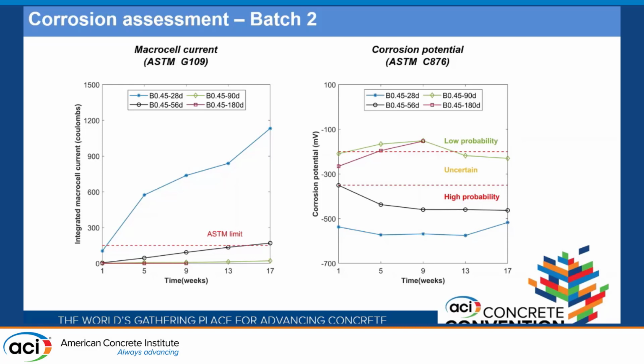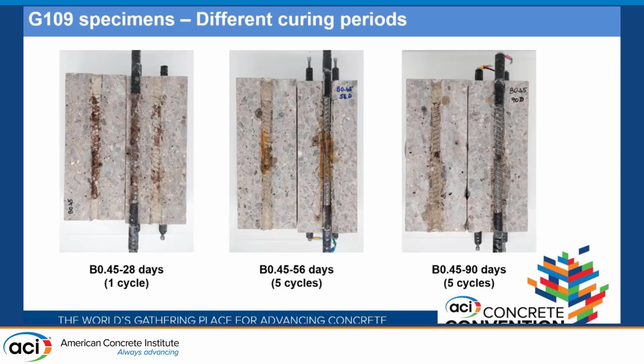So after 5 cycles of exposure, I autopsied all the specimens, and this is how it looks. The first one was with just 28 days of curing and just 1 cycle of chloride exposure. And for the other ones, it is with 5 cycles of exposure and 56 days and 90 days of curing. You can see that there is significant improvement in the corrosion performance. There is comparatively much lower corrosion here.